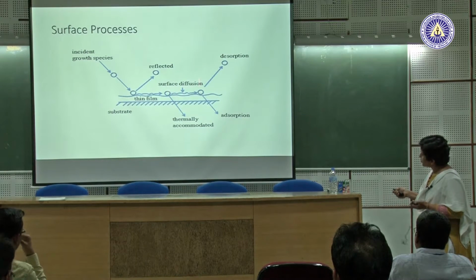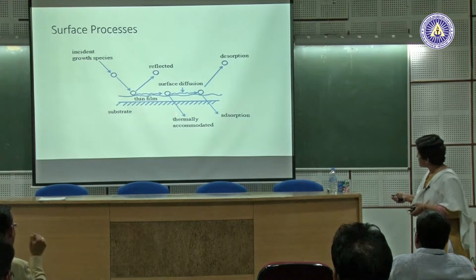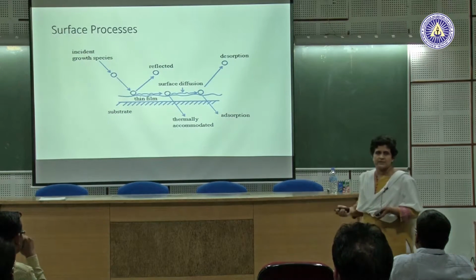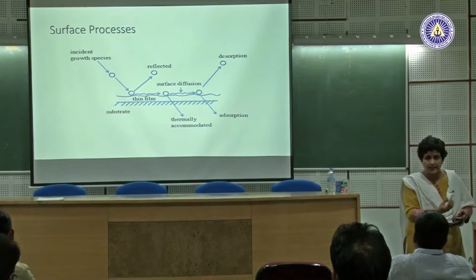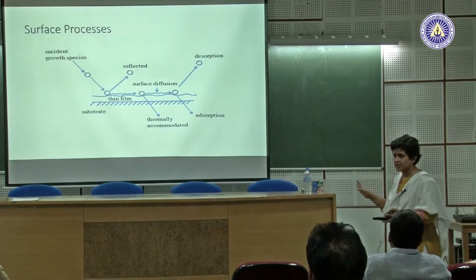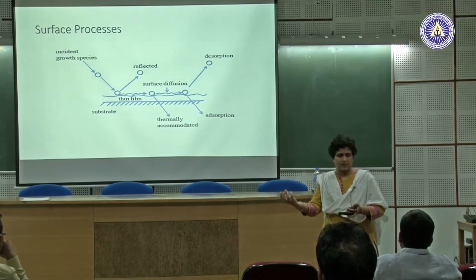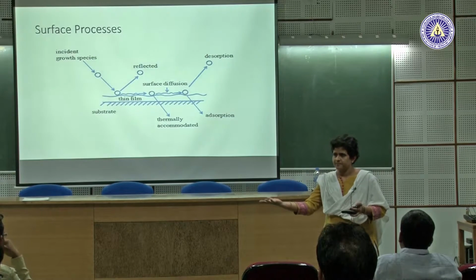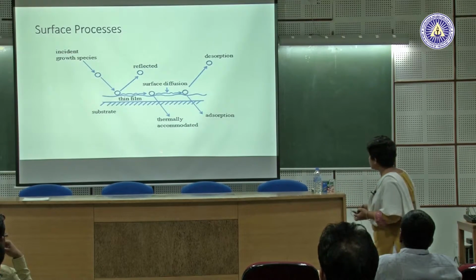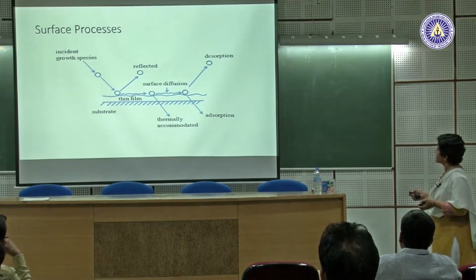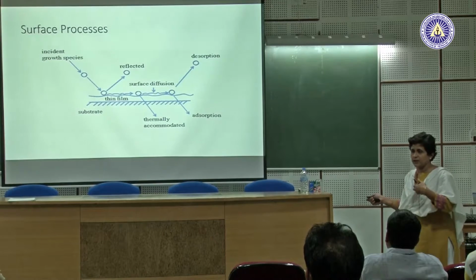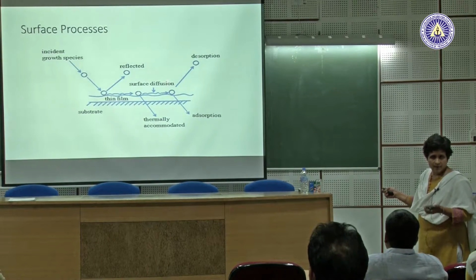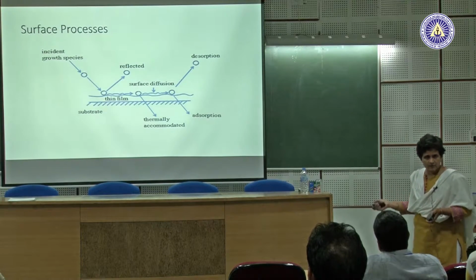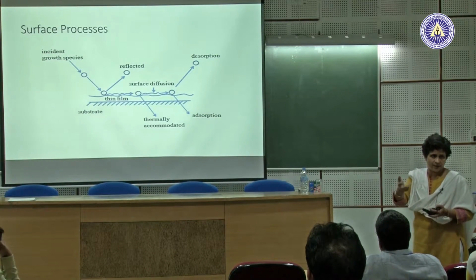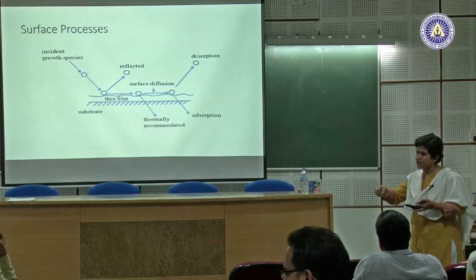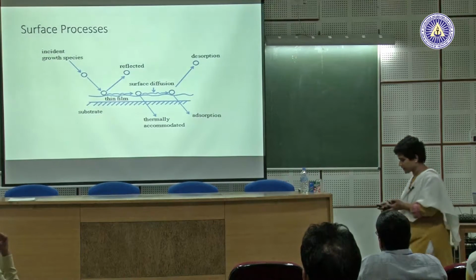At some point, it can lose all its energy by collisions and other ways, and it becomes thermally accommodated. The word thermally accommodated means that the atom which was evaporated at a higher temperature and had a higher energy has lost its excess energy and has become the same energy as the thin film, and now it becomes part of the film. Or it can continue to diffuse, because on the surface you can adsorb and desorb things. It can desorb if the temperatures are high, and at some point it can also get adsorbed by forming a chemical bond, if a chemical bond is possible between these two species, or by getting physisorbed or chemisorbed on the surface. Okay, that's how it will take place.